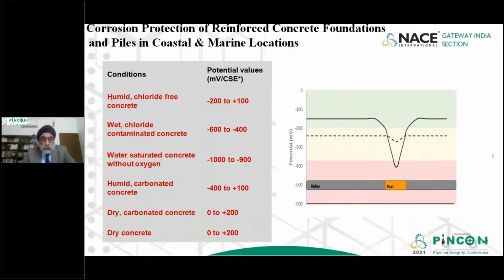So depending on the status of the concrete, it can either be humid but chloride free. So if we measure potentials between minus 200 to plus 100 millivolt with respect to a copper sulfate electrode, it gives us an indication that the concrete is chloride free. If we are measuring potentials between minus 600 to minus 400, we know that the concrete is chloride contaminated. If we are measuring between minus 1000 to minus 900, the concrete is saturated with water, but there is no oxygen.